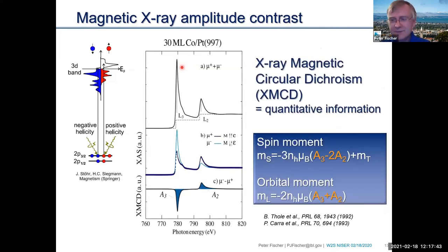XMCD, X-ray magnetic circular dichroism. You basically take photons with a specific energy and a certain helicity, and you shine them onto the magnetic materials. Once the photon energy that you apply, you basically have a monochromator and you just vary the photon energy, once it matches the binding energy of this inner core electron, this electron gets excited. And the difference between optical Kerr microscopy and X-ray magnetic circular dichroism spectroscopy is that the states involved with the X-rays are very localized, well-defined 2p 3/2 states. So we know exactly that the signal in this absorption profile, that means the interaction, the transmission, the absorption, is 100% coming from that electron down here.